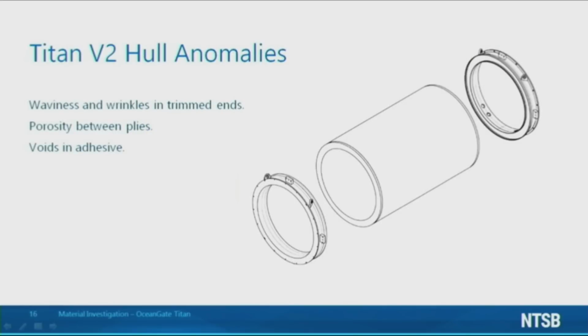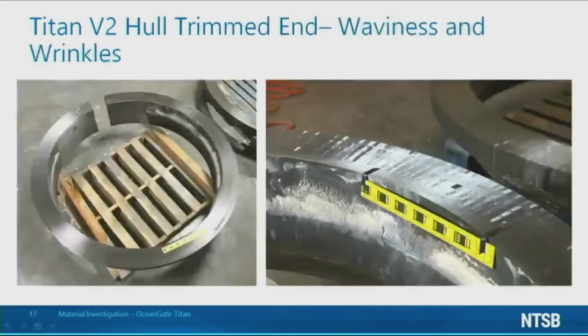The materials group examined trimmed end pieces and a recovered piece of the V2 hull and found waviness, wrinkles, and porosity within the composite layers and voids within the adhesive that joined the layers. The Titan hull exhibited waviness and wrinkles within the hull layers, especially the second through the fifth layers.